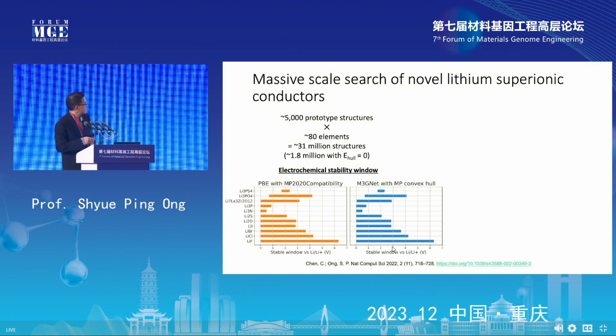And basically what we did was to generate about 31 million structures. We found that about 1.8 million of them have an E-hull of 0. In other words, they are predicted to be stable on the convex hull. We can calculate things like the electrochemical window. On the right here is what you get with M3GNet. On the left here is what you get with a DFT calculation. And you practically can't tell the difference between the M3GNet prediction and the DFT calculation, okay?